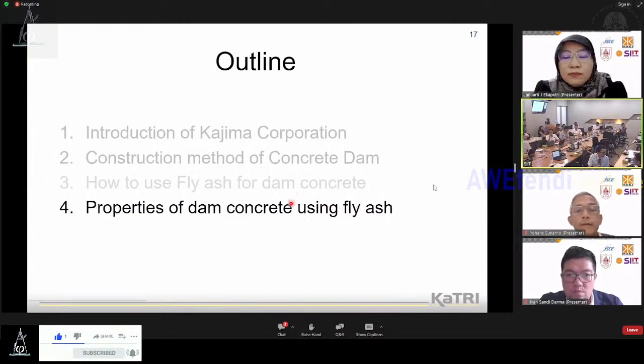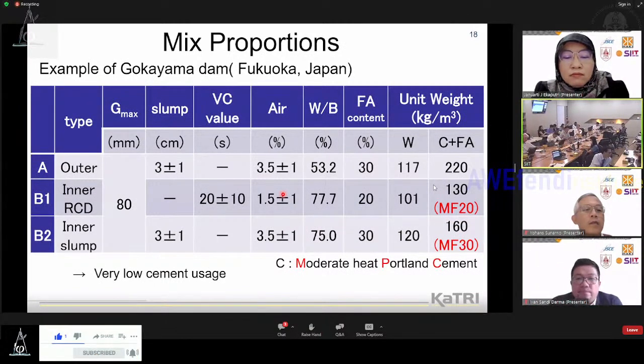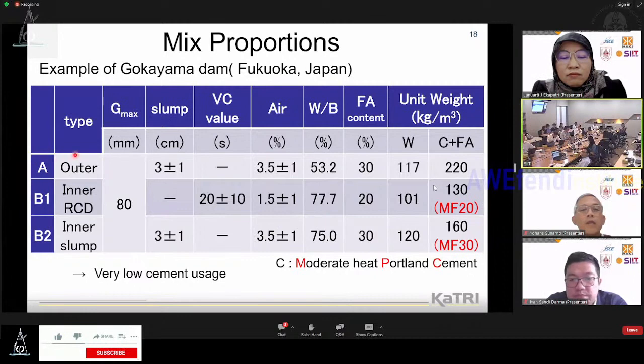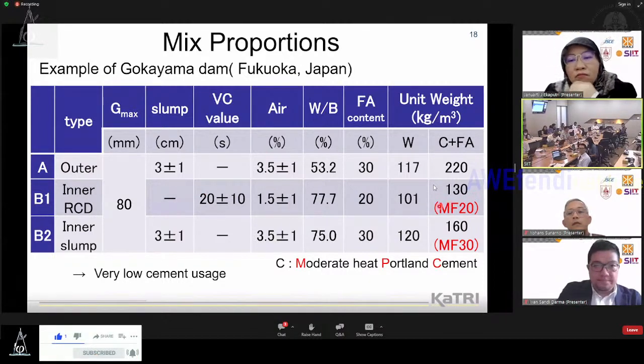Okay. Lastly, I will explain the properties of dam concrete using fly ash. This shows the mixed proportion at our dam site, the example of Gokayama Dam in Fukuoka, Japan. Number A is the outer concrete, where the water binder ratio is 53.2 and the FA content is 30%. We use moderate-heat Portland cement and fly ash cement, and we call this type of cement MF20 or MF30. The outer part needs durable concrete, so the unit weight of binder is 220. On the other hand, for the RCD inner part of the concrete, 130 kilograms per cubic meter is used.